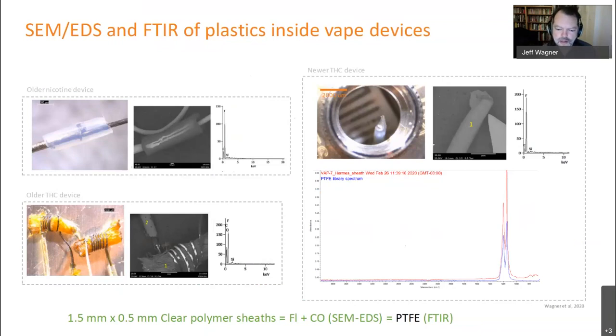It really depends on exactly how high the temperatures are getting in these devices, but there have been many studies that have documented the hazards of heated PTFE, especially in industrial scenarios. But in this case, if temperatures get up to 300 degrees Celsius, most of the studies have shown that you're in danger of liberating some type of fluorinated gases. But that is a big question mark. It is possible that these devices stay below 300 degrees Celsius, and we're currently looking at that issue.